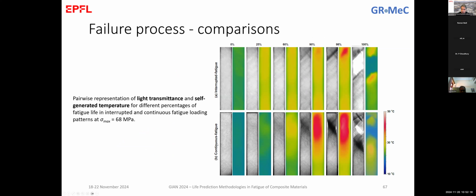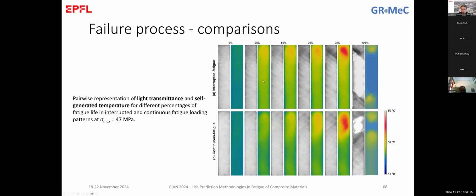And you see in the continuous fatigue, we have damage that is concentrated, and these are the same photos as before, concentrated and leading the material to failure. But in the interrupted fatigue, the damage progress in the specimen, even at high stress levels, here at 68 stress levels, is similar to the damage progress that we had in continuous fatigue at low stress levels. It is more spread, more distributed over the material. And this is, of course, the reason that makes the material sustain more loads during the damage.